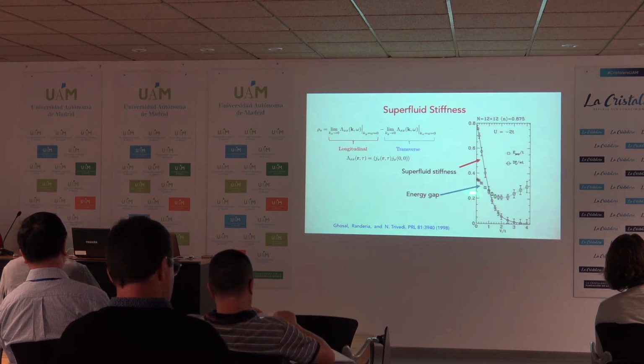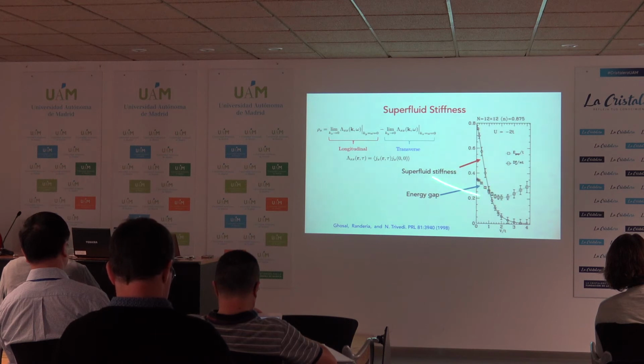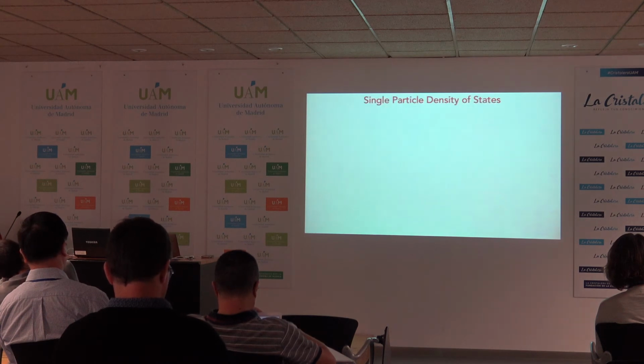And that's what is shown here as a function of disorder. The single particle gap remains finite, so the amplitude is not going to 0. But the superfluid stiffness, precisely because of these patches which are getting uncorrelated due to quantum fluctuations, is decreasing and vanishing at some critical point.